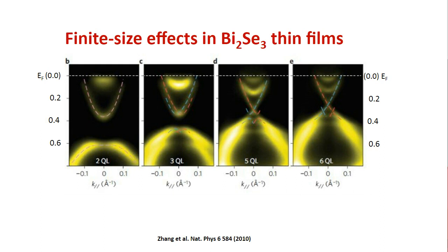And you can also see another thing that's happening. Of course, we are zooming in to the surface states. We are not showing the bulk, but the bulk states are just above and below those surface states, so they are also getting pushed up and down. You can see this bright yellow feature. Those correspond to the bulk states. For the valence band, the bulk states are getting pushed lower, and for the conduction band, the bulk states are getting pushed higher. So the bulk gap is also changing. And this gave us the idea: can we measure this through optical spectroscopy?